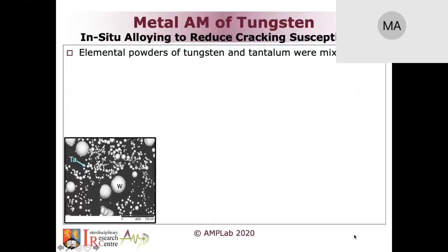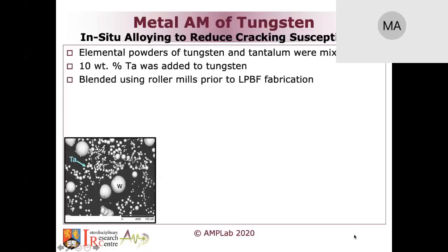If the alloying element that you're adding has particles which have the same size as the parent particle, then you may sometimes have some issues with homogeneity. So in our case, we did the blending in such a way that you have fine tantalum to fill the gaps between the large tungsten. Essentially, it's just tubular blending, blended in roller mills. We didn't do any special blending, just simple blending, and that was sufficient to allow us to get a homogeneous mix as you saw in the results.